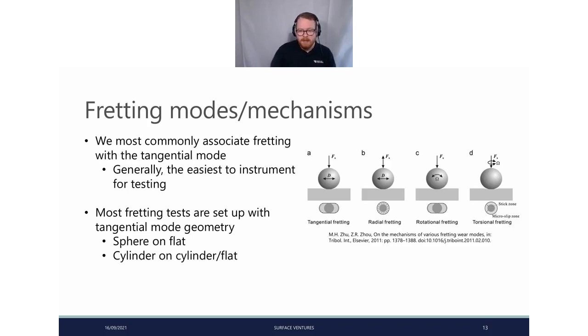Fretting modes and mechanisms. So I sort of alluded to the fact that there are different types of movement associated with fretting wear. Most often we think about tangential mode, because this is one of the easiest things that we can instrument, that we can put in a machine and test, because essentially we're putting in this example a ball on a surface and moving it back and forth with varying amplitude.